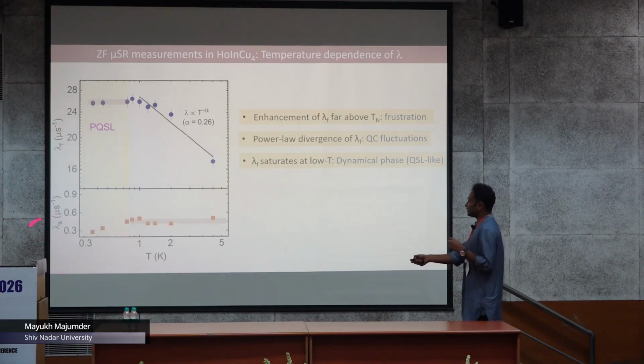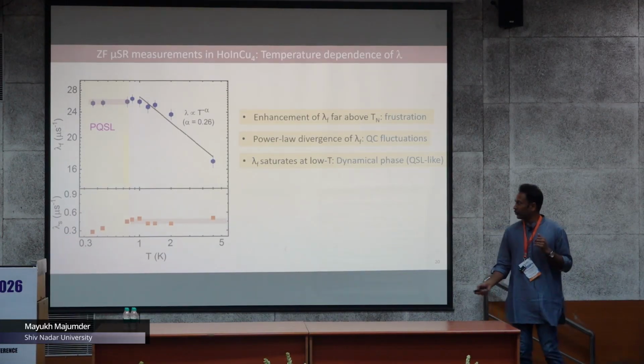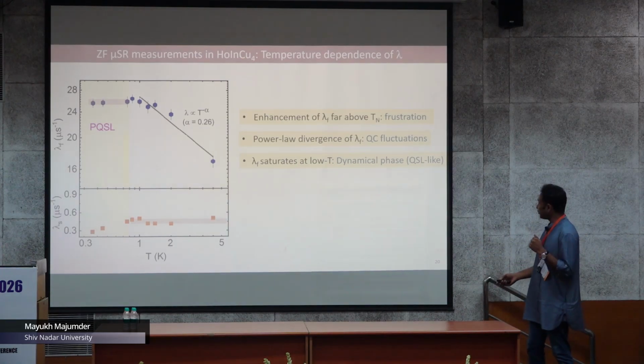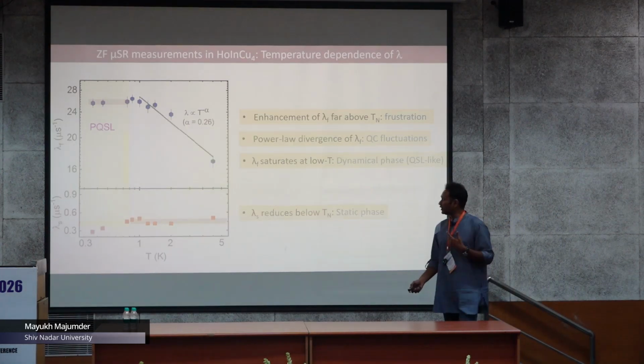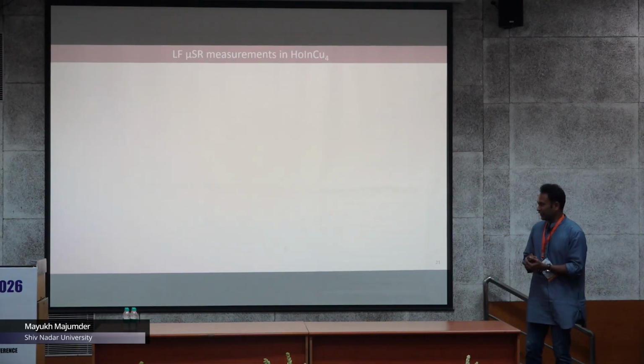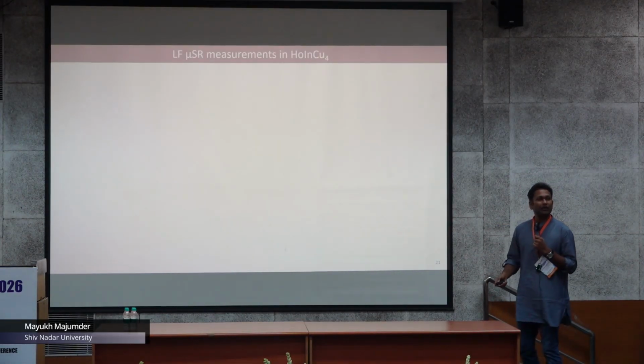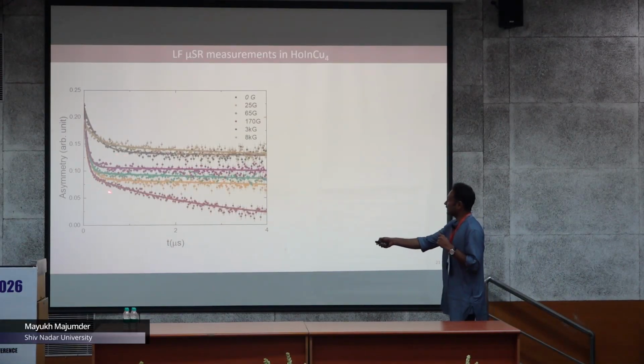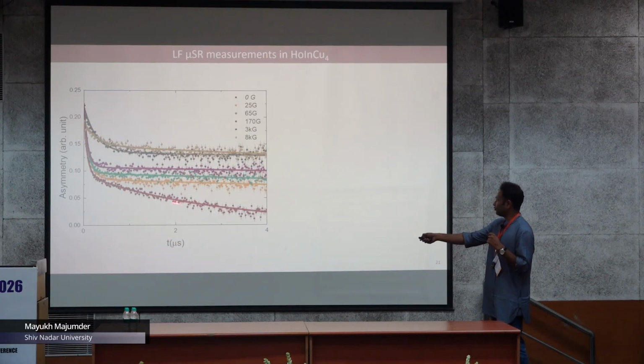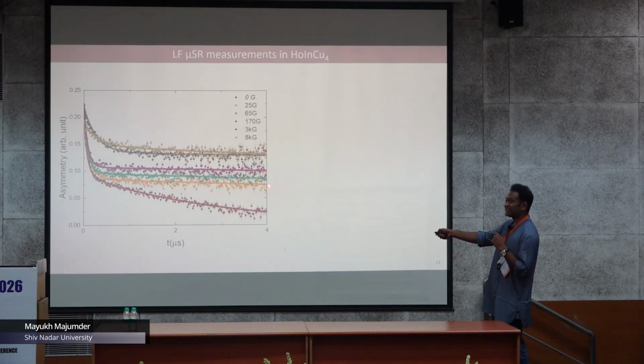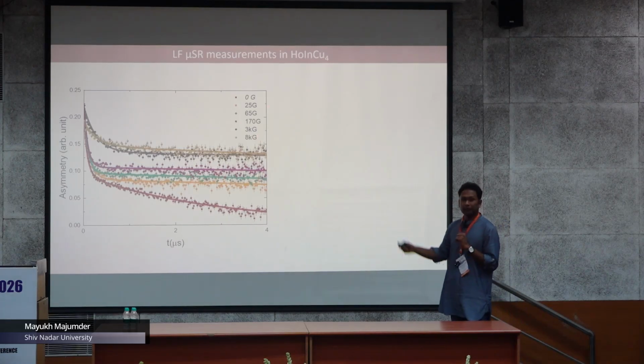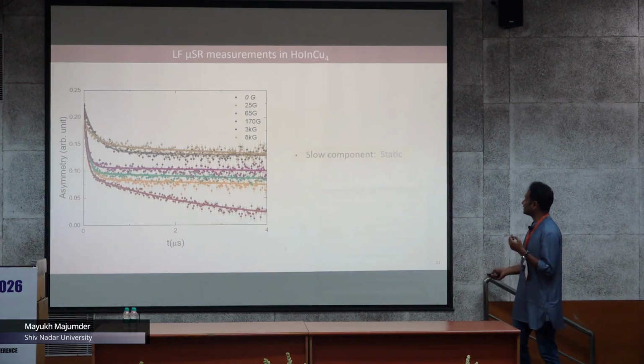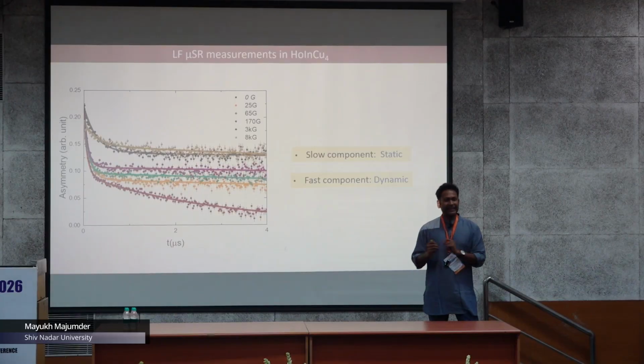Whereas lambda s, the slow component of this lambda, reduces below Tn, probably indicating some static phase. So this was further verified by the longitudinal field experiment. Let me show you quickly that this is the sharp component. So this is the zero field data, the brown one. You can see by the application of 25 Gauss, the slow component completely gets saturated. Okay, so indicating that the slow component is associated with static correlations, whereas the fast component is never going to be decoupled even after a field of 8,000 Gauss. So this further tells you that you have a coexistence of both static and dynamic type of